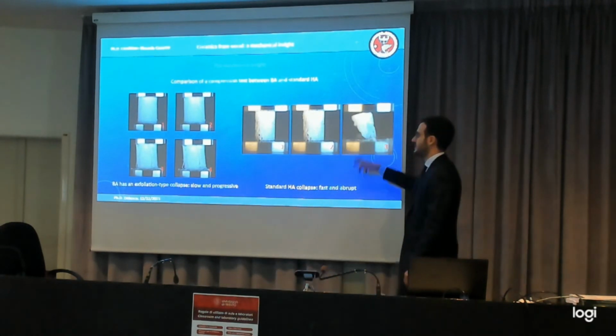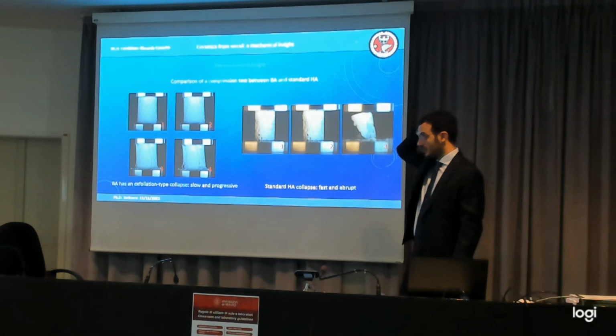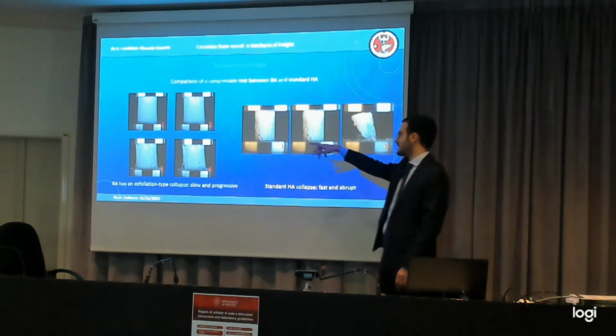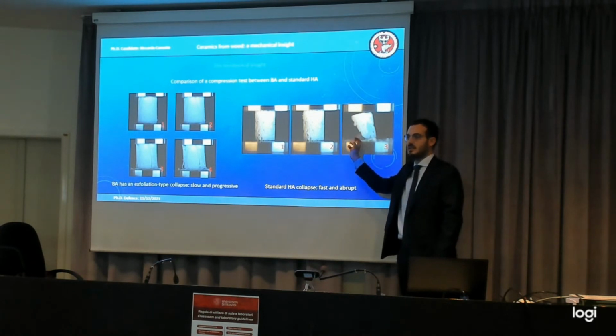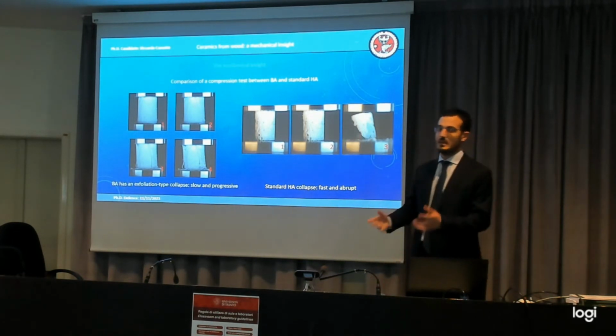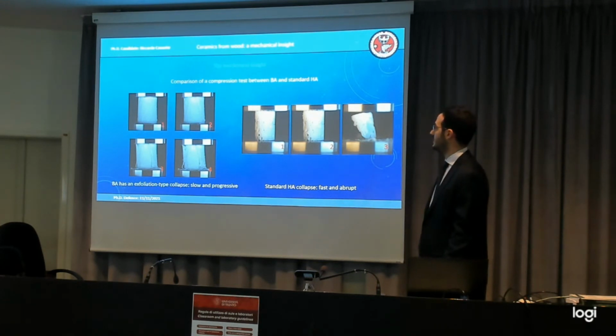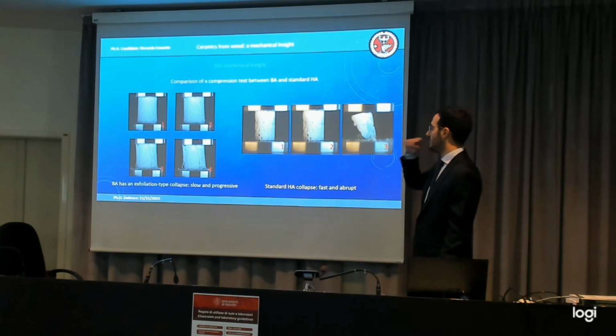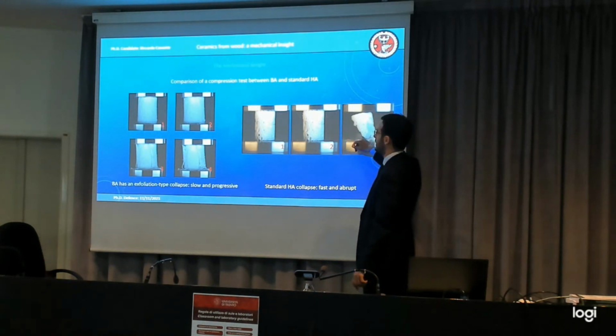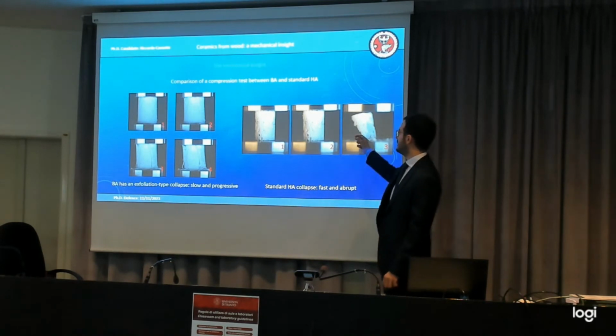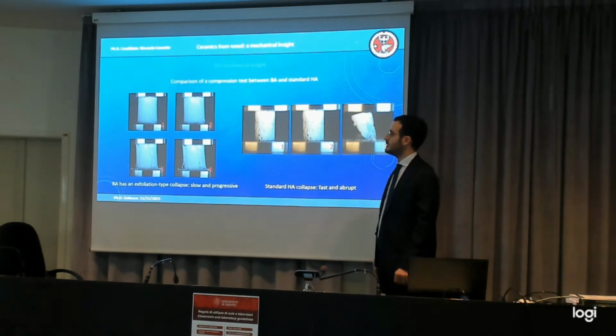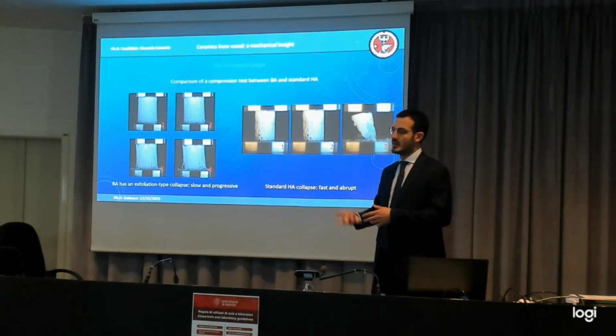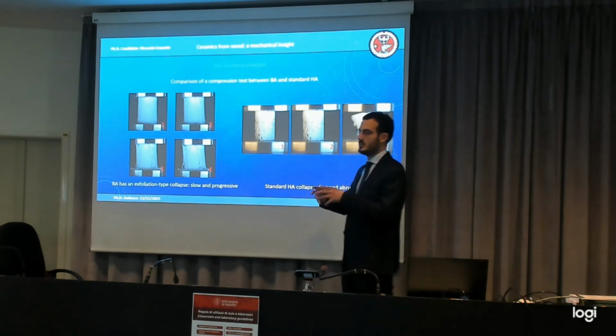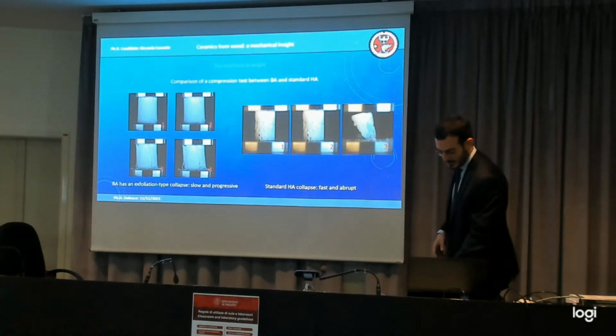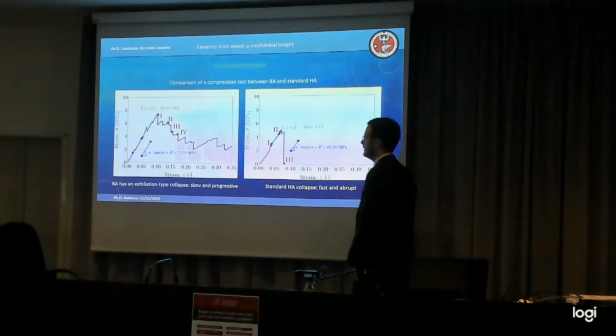We can see how the bioapatite fares in comparison with standard hydroxyapatite. The difference is that the hydroxyapatite over there is the one obtained from rattan wood, from the chemical transformation. This one is the control. This is standard hydroxyapatite. It does not have any preferential direction in the organization of the crystals. And then you can see from the pictures, it's immediate to witness that there is a very brittle behavior exhibited by the control, and the bioapatite has a slower and progressive failure, which depends on this exfoliating type of failure happening in the contour that slows down the crumbling, for example.